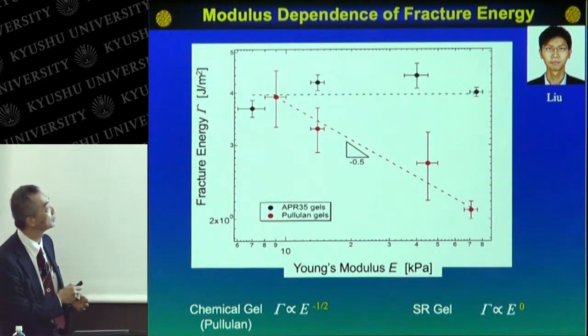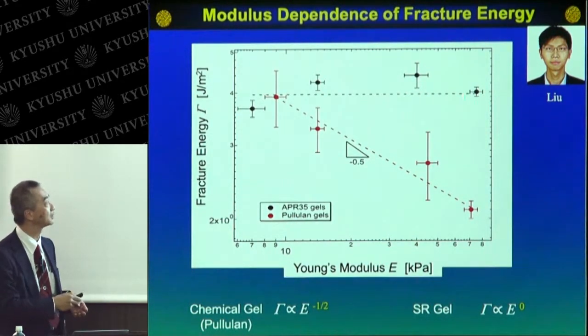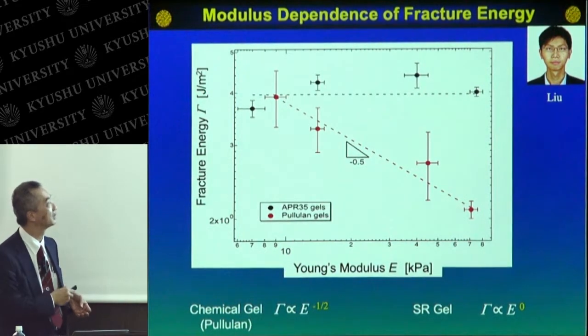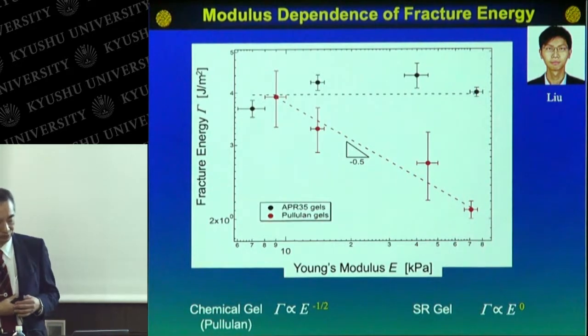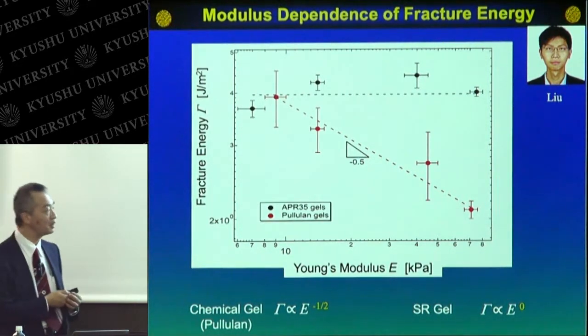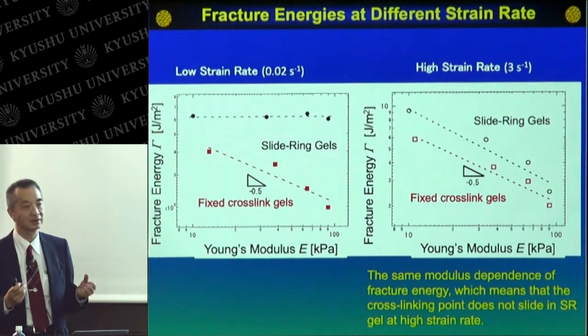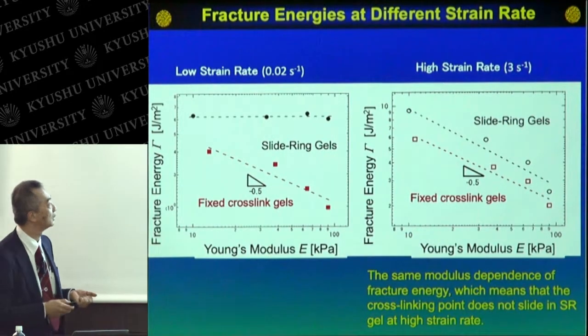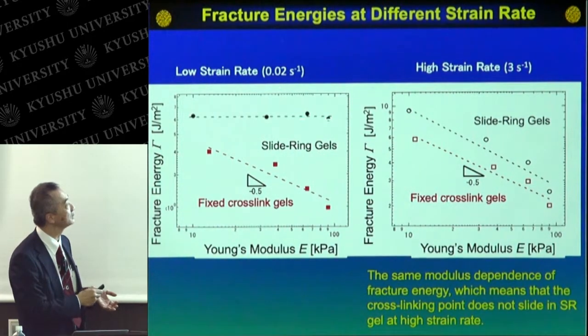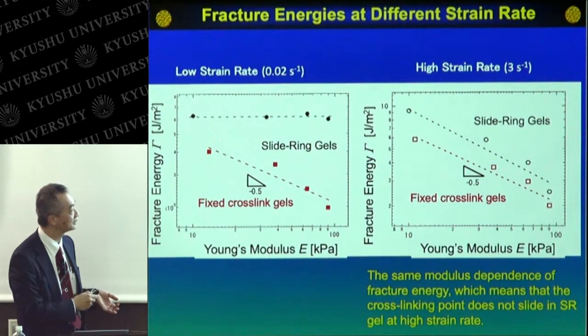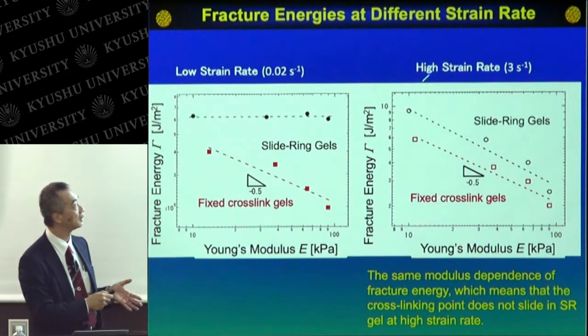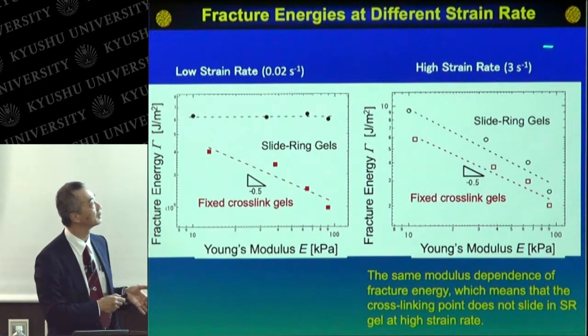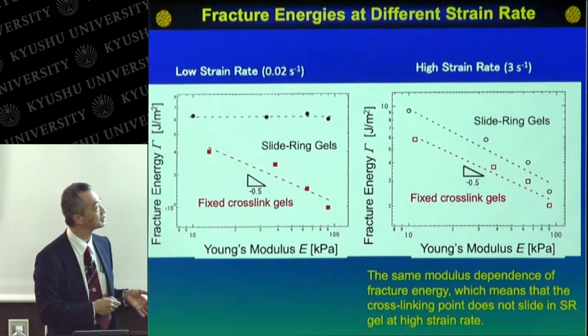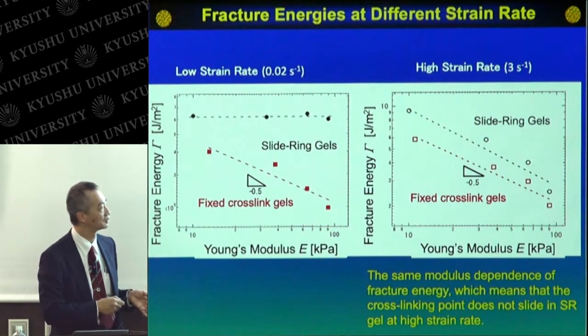On the other hand, sliding material shows a quite different feature. At the higher Young's modulus, it still shows a higher fracture energy. This is quite different from the usual chemically cross-linked materials. But this behavior is strongly dependent on how fast the sliding gel is elongated, stretched. At a low strain rate, this sliding gel shows a higher fracture energy than the fixed cross-linked gels. But at a much higher strain rate, about 100 times higher, it shows almost the same behavior of the fracture energy on the Young's modulus side.